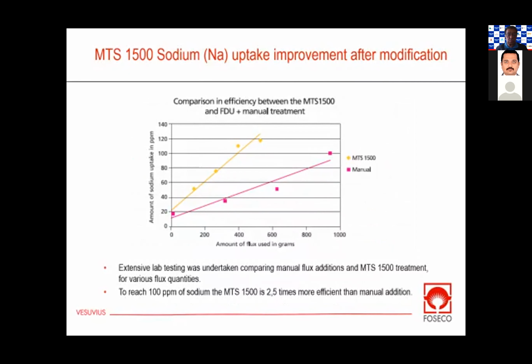And what you see here is we increase the amount of flux used on the x-axis, anywhere from 200 to 1 kilo of flux of a sodium modifier. And we measured the sodium pickup that we have in the melt.